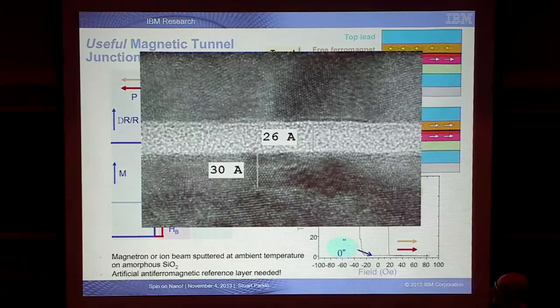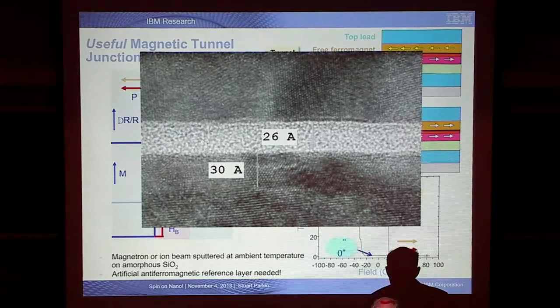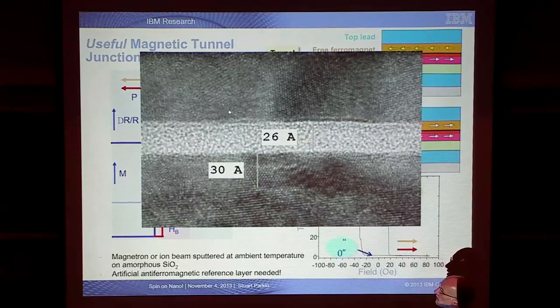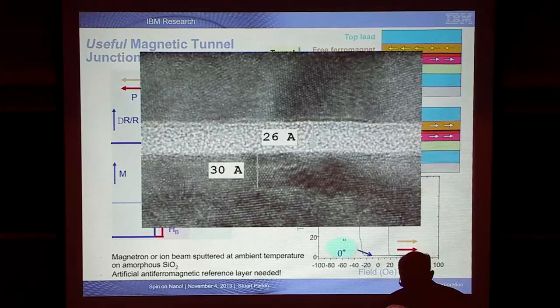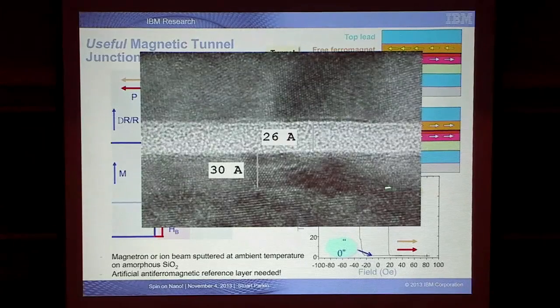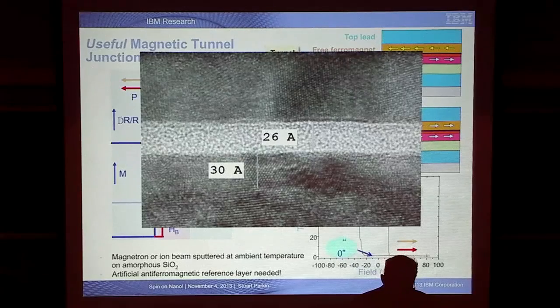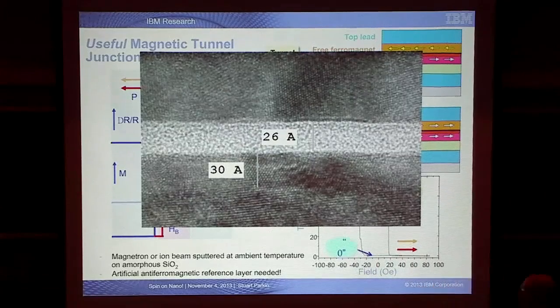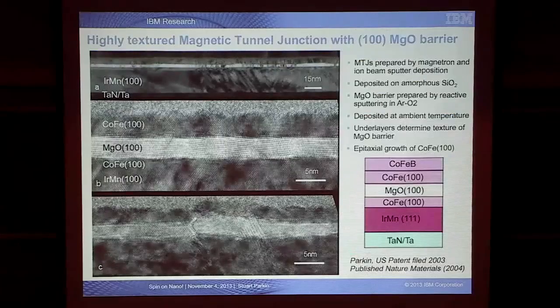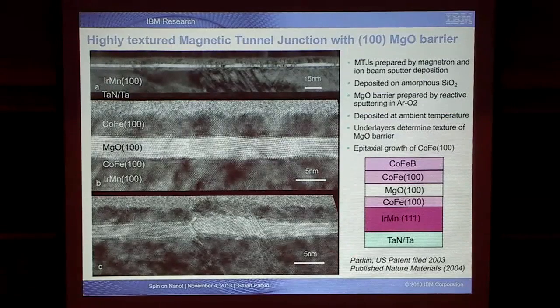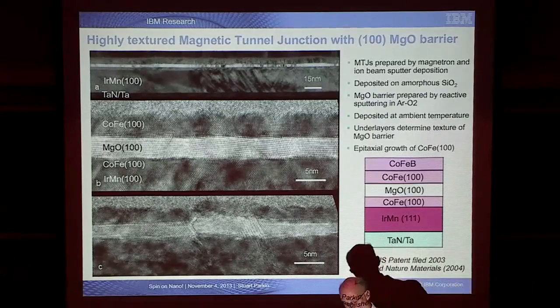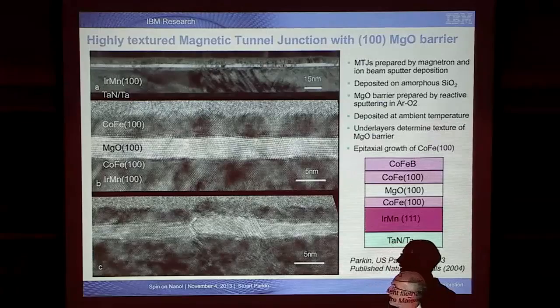This material is used because it turns out that to create useful tunnel junction devices where we can measure some current, this barrier, this insulating layer, has to be very thin, a few atomic layers thick. Otherwise, there's no current. The probability of tunneling across the layer is too small. And aluminum oxide was a material that was discovered in the 1980s, could lead to the ability to make devices for superconducting Josephson junction-based computing devices that IBM and Hitachi were developing. And so this is the insulating material that we initially used for these magnetic tunnel junction devices. Now, it turns out that there's a better oxide material that we first showed in 2001 could replace what till then was the best known material, this aluminum oxide. And this is a very simple oxide.